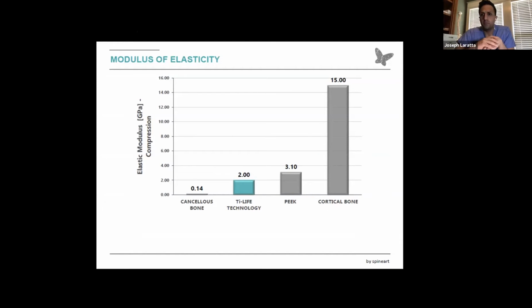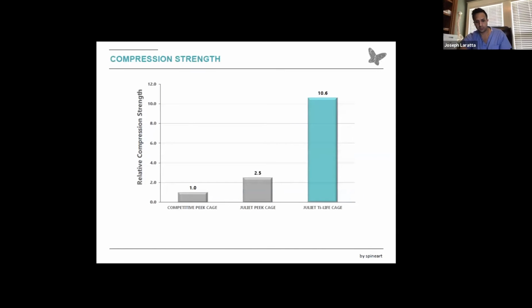One of the beauties of PEEK was that its modulus of elasticity was somewhere between cancellous bone and cortical bone, but much closer to cancellous bone. And subsidence, we think, has a lot to do with the modulus of elasticity and that difference between trabecular bone and the implant itself. Modulus, as we know, is the slope of the stress strain curve, but it could also play a role in something called mechanotransduction, which we'll touch on a little bit later.